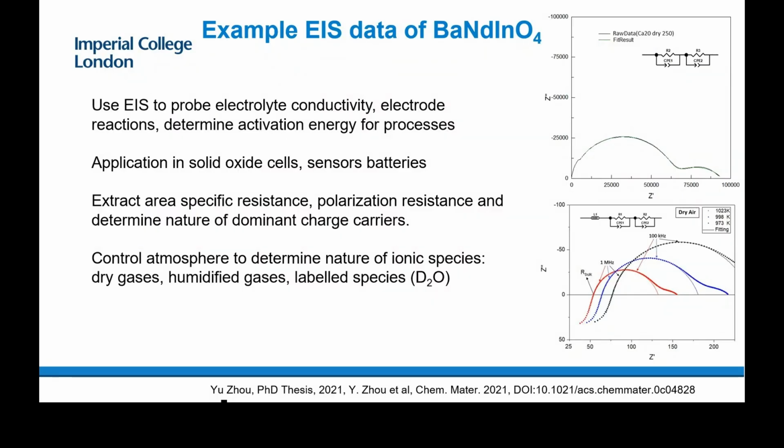All right, so first of all, on the real part of the impedance. I can see there is some resistive behavior at the beginning. So it starts at 27 or 30 ohms, let's say. Yeah, these ones here. That would be from the current collector, some resistivity from the current collector. As you go up in temperature, and you're operating at these higher temperatures, you lose the capacitive component from the bulk and the grain boundary. So you don't see an arc for the bulk and the grain boundary as you go to higher temperatures.